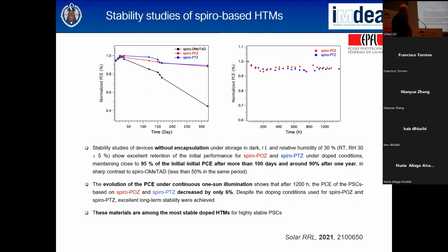In terms of stability, now people say 30 days after, no. Now, in terms of stability, we carried out this study over 300 days, almost 1 year, okay? And after 1 year, our molecules retain 90% of the efficiency in the dark, at 30% humidity, okay? Look at this, this is the spiro. Spiro is less than 50%. So this is a tremendous difference between these.